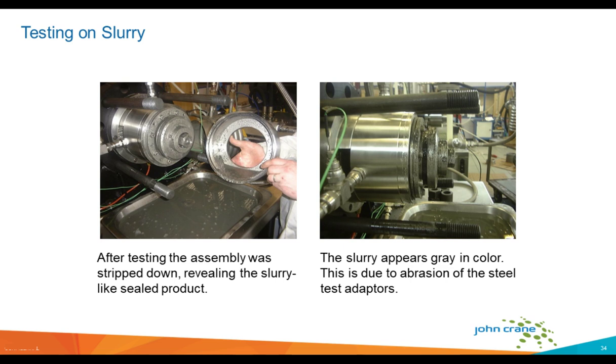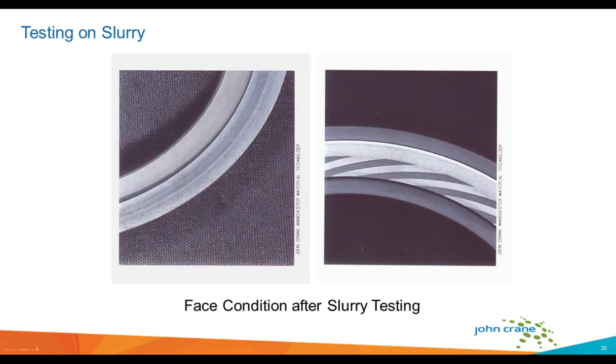John Crane's done quite a bit of testing with USPs on some very significant applications, such as slurry applications, and you can see this is kind of a stripped down post-mortem of the slurry seal rig, and you can see a lot of the abrasive wear and damage to the rig components themselves, just due to the nature of the slurry, very abrasive particles. So what the thought here was, and the intended goal was to test the USP technology and see if the seal faces would suffer any adverse effects from being exposed to a very arduous duty, which is the slurry duty.